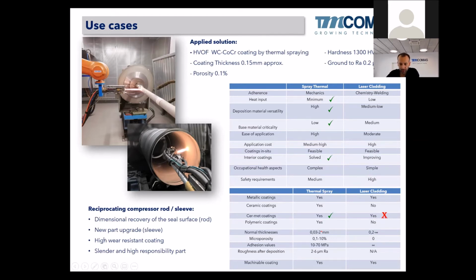In both cases, the customer asked for high wear resistant coatings, and in both cases we have slender, high responsibility parts, easy to distort in case of very high heat input. So the applied solution was HVOF thermal spray, high velocity tungsten carbide cobalt chromium coating, with a hardness of 1,300 Vickers. Coating thickness was about 0.15 millimeters, 150 microns. Porosity 0.1 to 0.5. It's HVOF, so porosity is low.